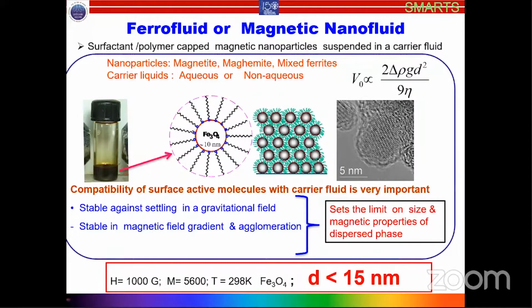Obviously, you can choose a highly viscous medium to delay the sedimentation of particles. That is what is done in the case of magnetorheological fluids. In magnetorheological fluids, you have micron-sized particles, so they use very highly viscous oils to keep these particles suspended. And obviously, they also use rheological modifiers. They are ferromagnetic materials. In this case, they are superparamagnetic materials. I'll talk about them.